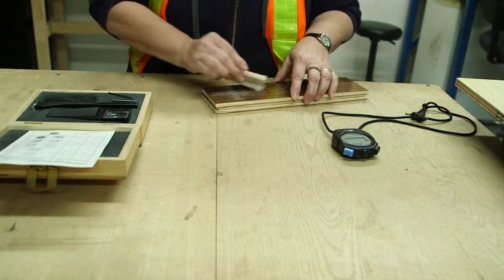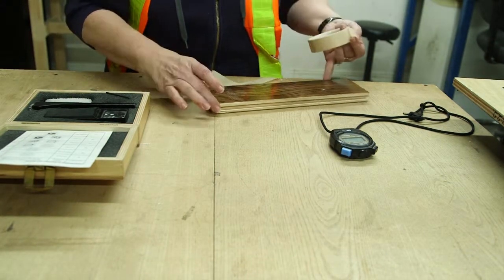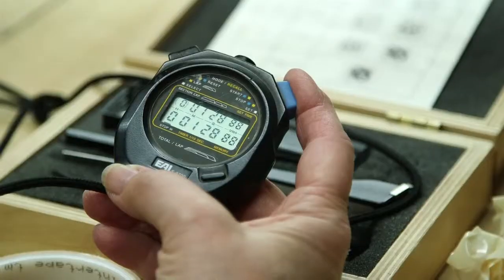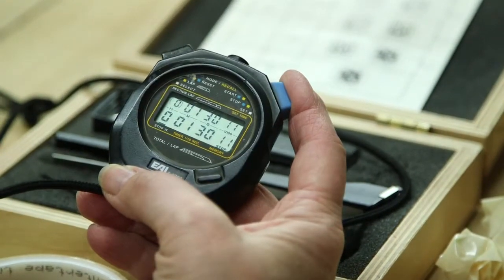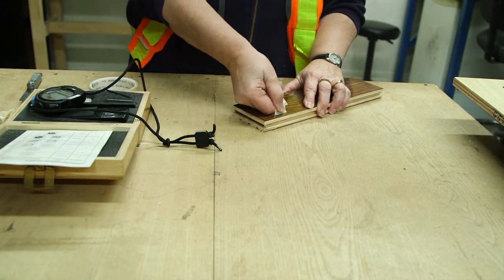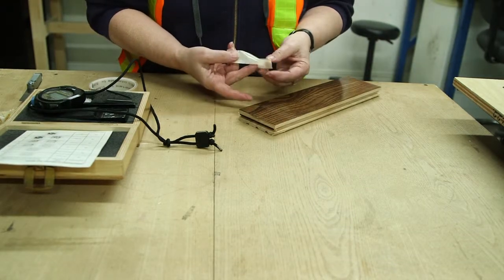You take a piece of wood that has finish on it. Essentially it's like making knife marks horizontally and vertically, so you have little squares. The idea is that none of the little pieces in those little squares should just flake up, so that if you still have those marks left but your finish hasn't flaked up, then it means that the adhesion is really good.